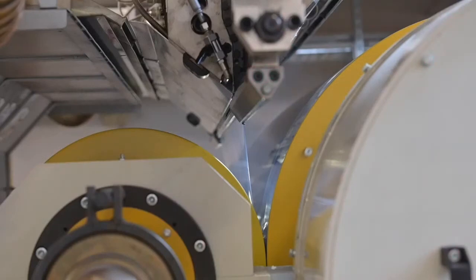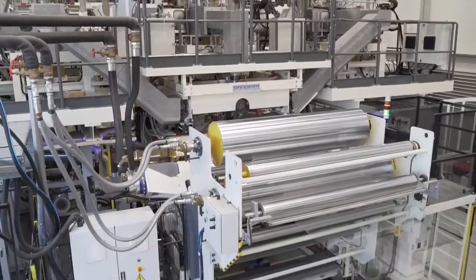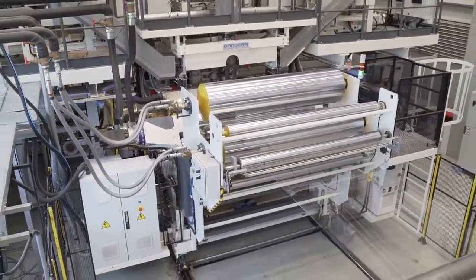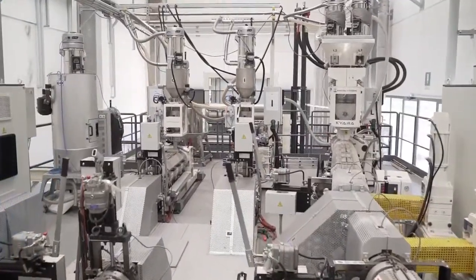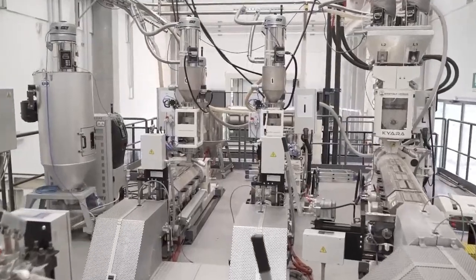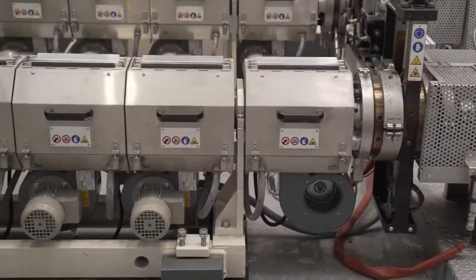The first one is a dedicated extrusion line with reinforced calendering to obtain transparent foil, glossy on both sides, with thickness values ranging from 240 micron to 1.8 millimeter. The second technology, which is more flexible and offers a wider application range, features a cast film line powered by a customized solution coating station to reach wider thickness range and higher transparency.